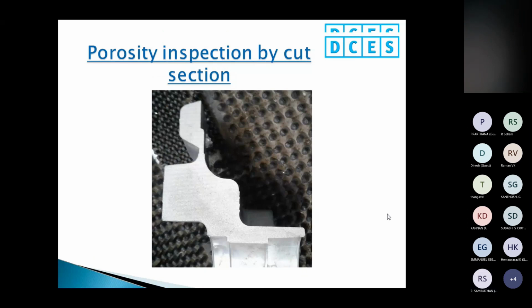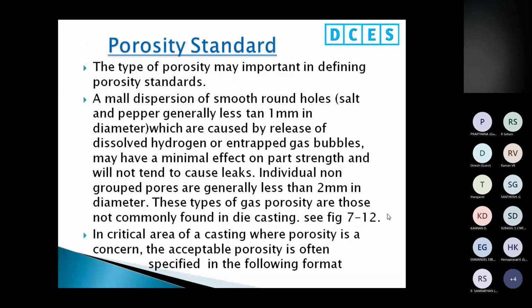Porosity standard. The type of porosity may be important in defining the porosity standard. A small dispersion of smooth round holes, salt and pepper, generally less than 1 mm in diameter, which are caused by a release of dissolved hydrogen in the molten metal or entrapped gas bubbles in the molten metal, may have a minimal effect on the part strength and will not tend to cause leaks. So sometimes smaller than 1 mm won't give much problem in the strength of the casting.